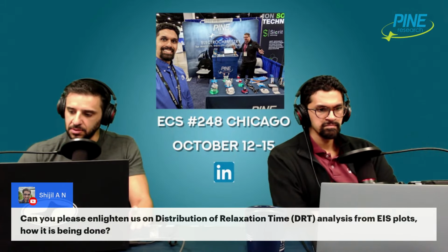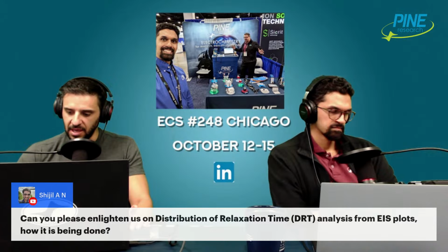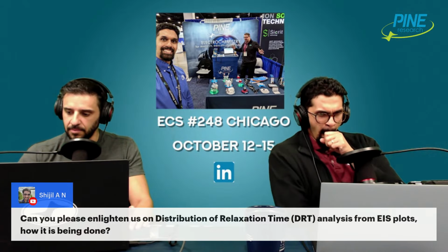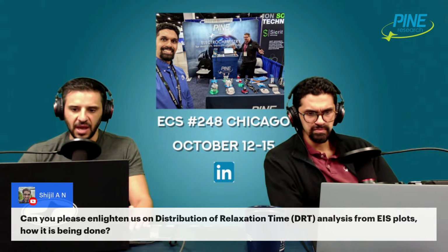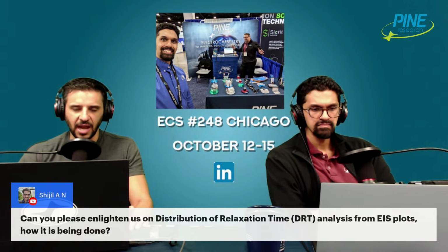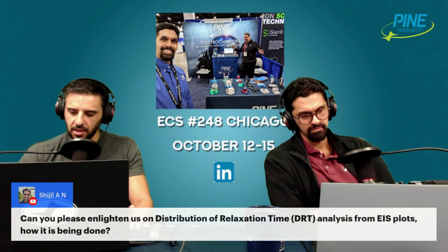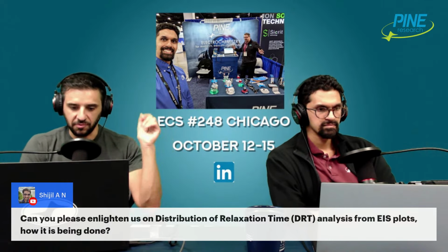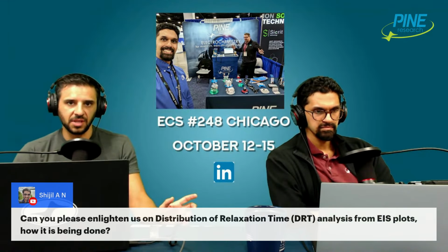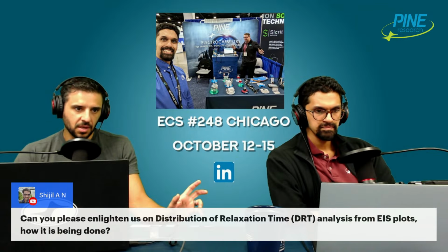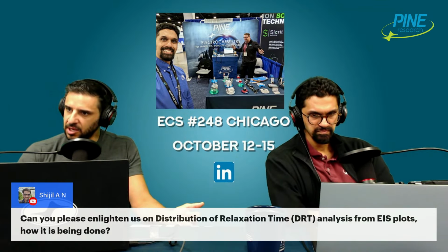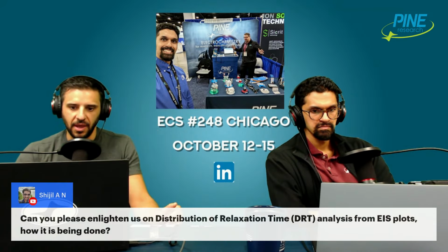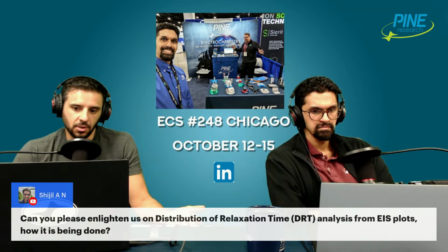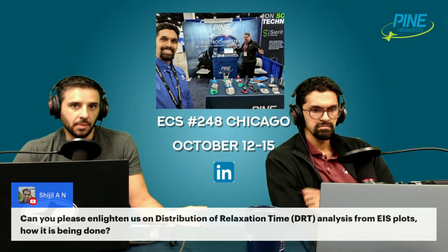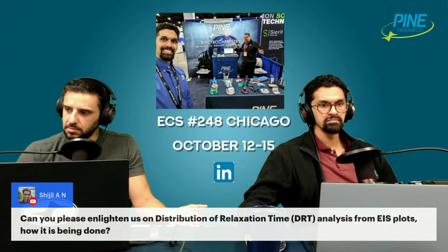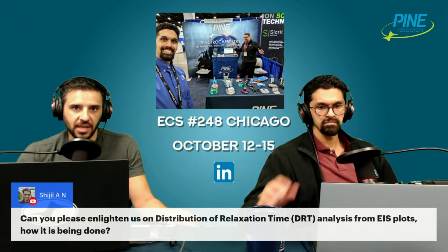The last thing I'll say is that there are absolutely limitations to this method and mathematical procedure. It is purely mathematical. There's not a lot of the theory behind it. In some cases, it's not as ironclad as other forms of analysis where you're trying to really connect with reality, some process that's happening. DRT is really a mathematical transform that presupposes some mathematical solution to your impedance data and then just casts it that way. Your presupposition could be incorrect, and so your data could be wrong. And one of the ways that it can be wrong is if you have a lot of capacitive behavior in your impedance data. DRT is inapplicable.